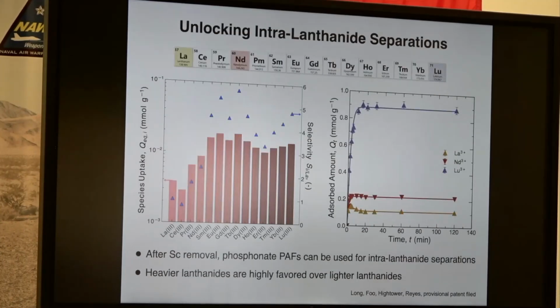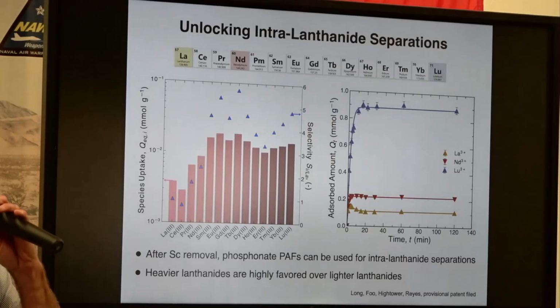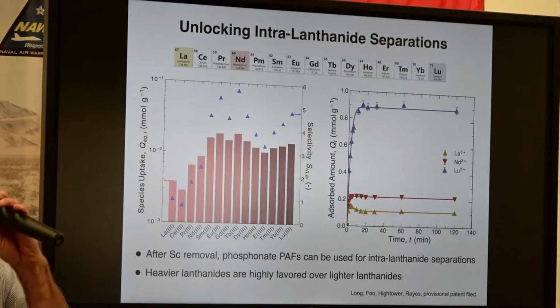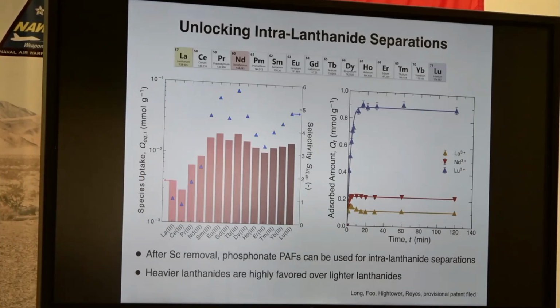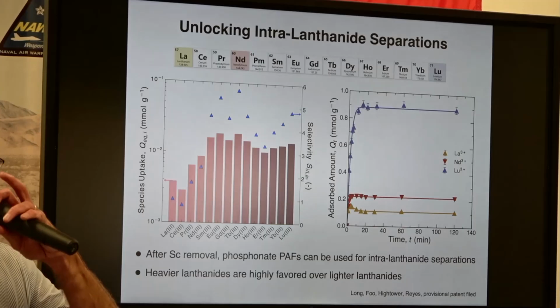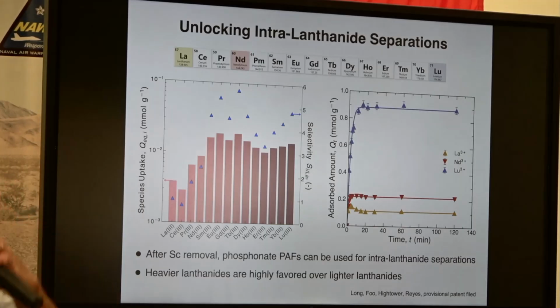Once you've removed scandium from those solutions, those adsorbents will next go after the highest charge density lanthanides. So you can start to pick them off, and for lutetium 3+, we've got quite good selectivity here. It's much better selectivity than the organic molecules in solution, in part because there's rigidity. The phosphonates in our material are much more rigid than those ligands in solution that are free to move. You can get much better size selectivity for metal binding if you have a rigid capture pocket.